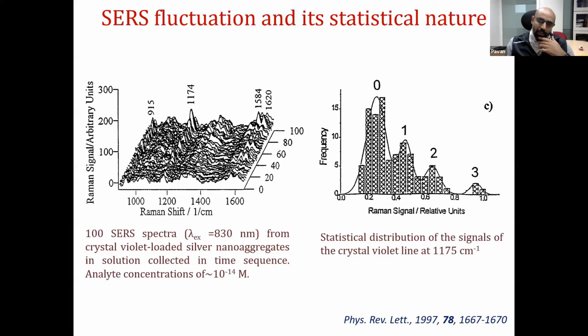This was one of the first reports of single molecule statistics in surface enhanced Raman scattering. It is very interesting that they first of all observed fluctuation in the Raman scattering signature. Second, they also studied the statistical distribution, and they reported a Poissonian distribution. But later on, people came to a consensus that this Poissonian distribution may not be the most accurate way of looking at this optical process, and that it requires a slightly more detailed analysis. Therefore, this approach has not been taken into consideration in the recent single molecule SERS community.